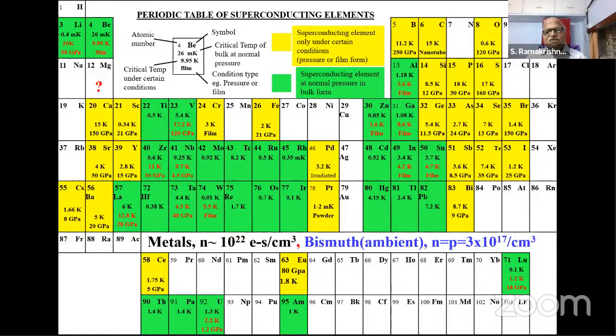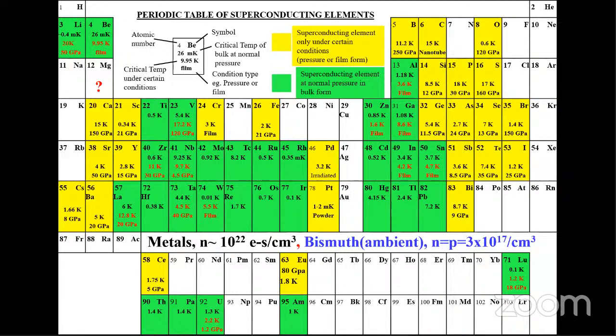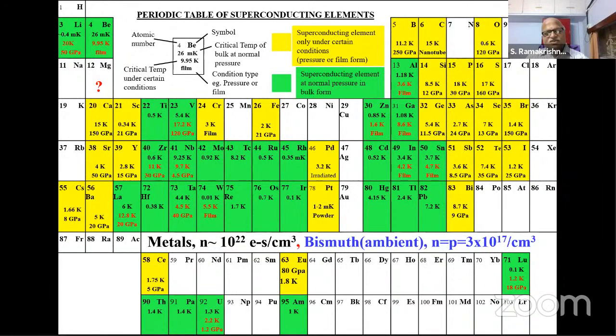In this case, bismuth is a really curious element. Unlike most metals, where the electron concentration is about 10 to the power of 22 electrons per cubic centimeter, bismuth is a semi-metal with an equal number of electrons and holes, and it has 5 orders of magnitude smaller electron concentration. So our aim is to see whether bismuth superconducts, and if it does, what is the mechanism for superconductivity.